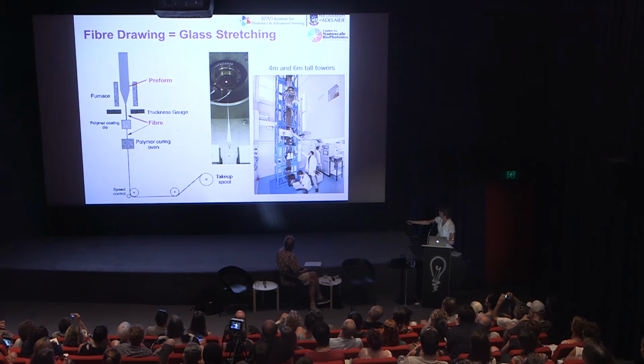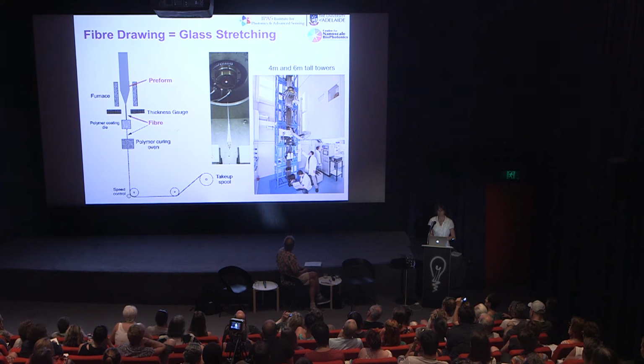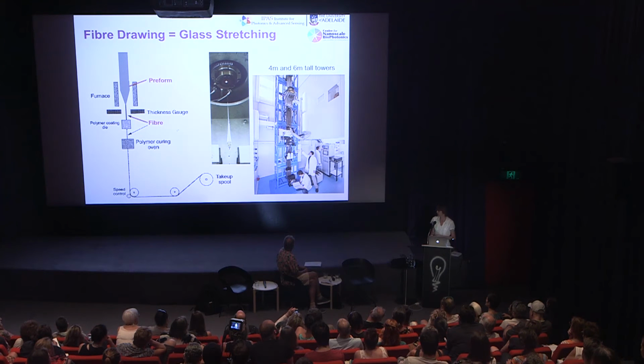Okay, now to the third step, what we are doing. Now we take the preform and place it again in a furnace. Now only a small part of the glass is heated up, and then it's stretched out to fibers that are as thin as a hair. And here, because now we stretch the glass, we want to get 500 meter or kilometer fiber, therefore the equipment gets taller and taller. So we have a 4 meter and a 6 meter drawing tower. Here you see a photograph of the beginning of the process, where the drop of glass is coming down, and in between the preform and the drop you have the start of the fiber drawing, so fiber is emerging.